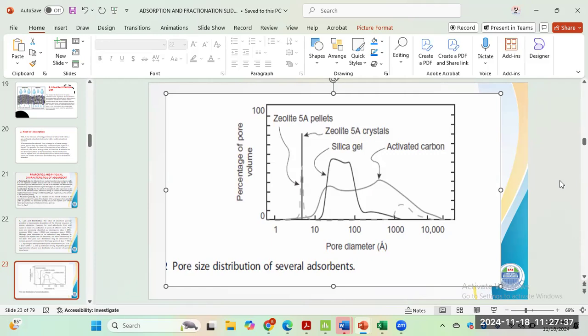So I also expected responses in terms of variation in the pore diameters of activated carbon, which is a big advantage, a big thumbs up to activated carbon. Yes, the pore volume may be low, but it can offer a pore diameter even lesser than the zeolite, though still very close to zero. Here, close to 10, you can still have a measure of adsorption, and then as it goes up to 10,000, as the pore diameter further increases, what happens? The percentage volume, depending on the process, drops. So it's used up gradually.